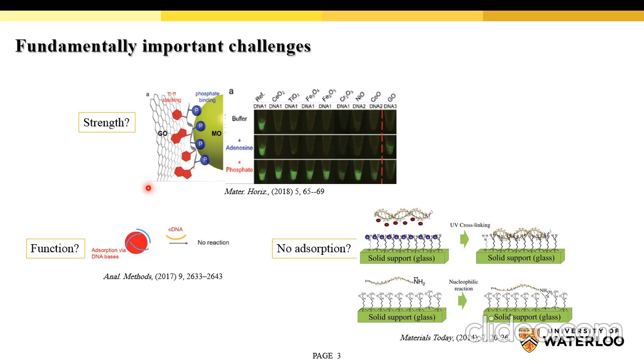For example, when DNA is adsorbed on graphene oxide, the interactions are weak, and DNA can be displaced by nonspecific interactions. On the other hand, when DNA is adsorbed on gold nanoparticles, it cannot react with its complementary DNA, since its bases are tightly adsorbed on the gold nanoparticle surface.